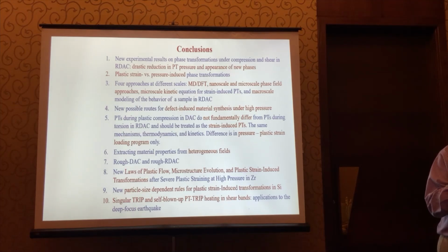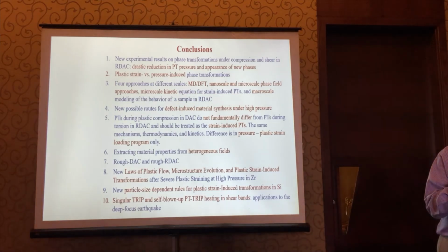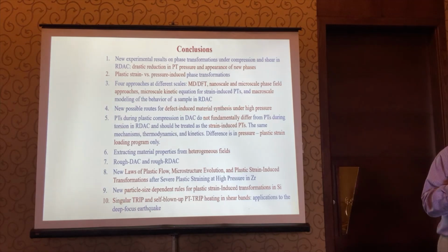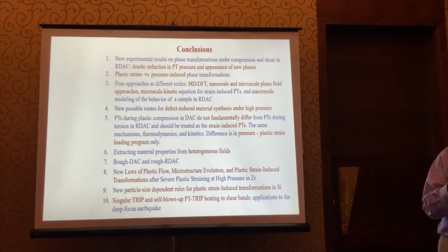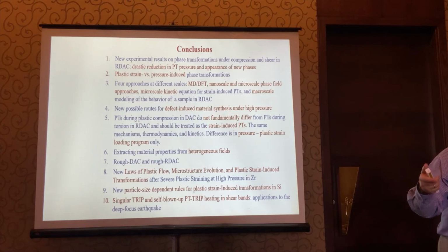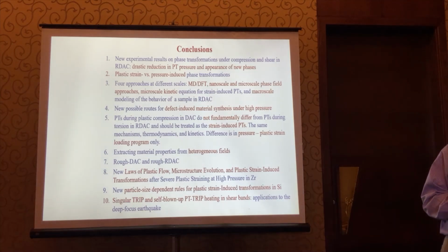But during plastic deformation, single crystal quite quickly transforms to polycrystal. And then grain size reduces. And the smaller the grain size, the smaller the phase transition pressure. But then we reach steady state in grain size and in dislocation density. And after this, transformation pressure does not reduce anymore. Yeah, so very strong effect of grain size.